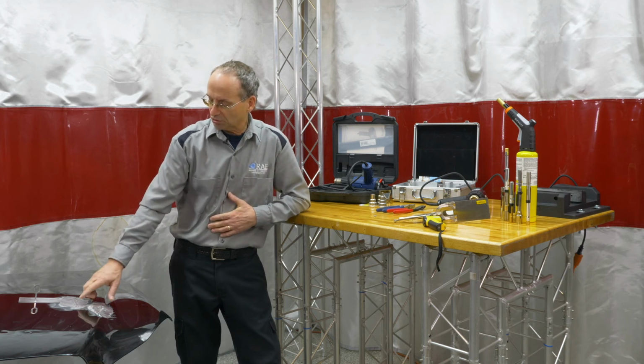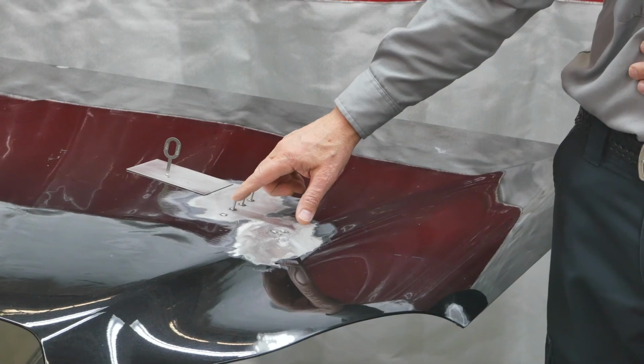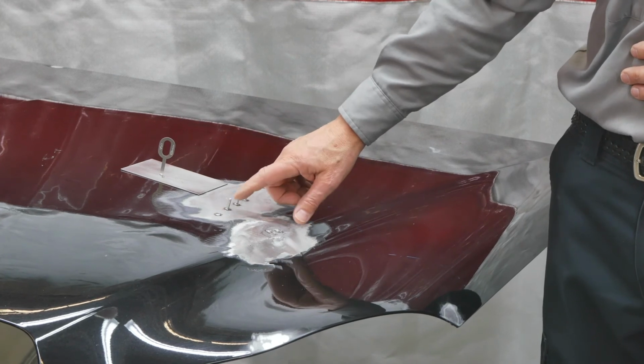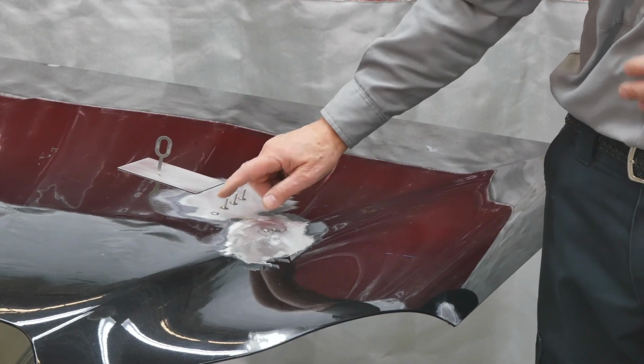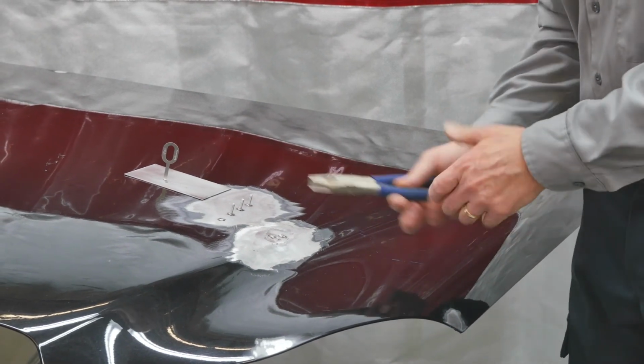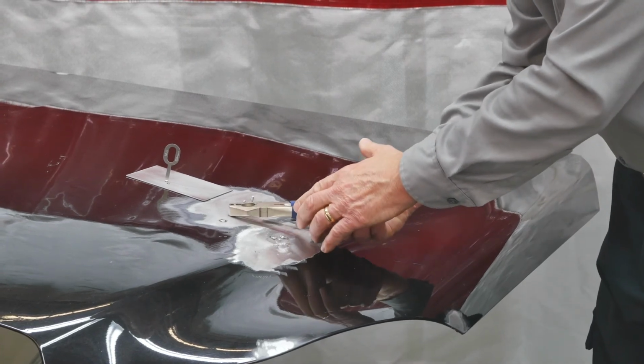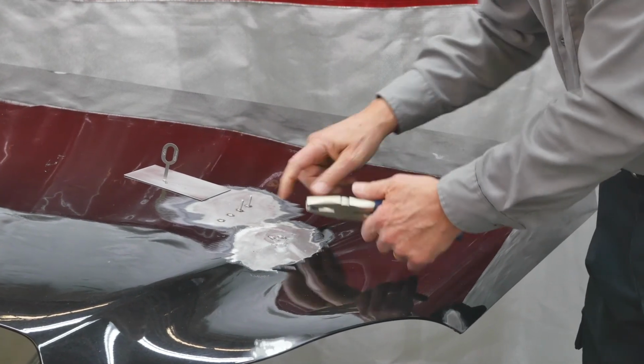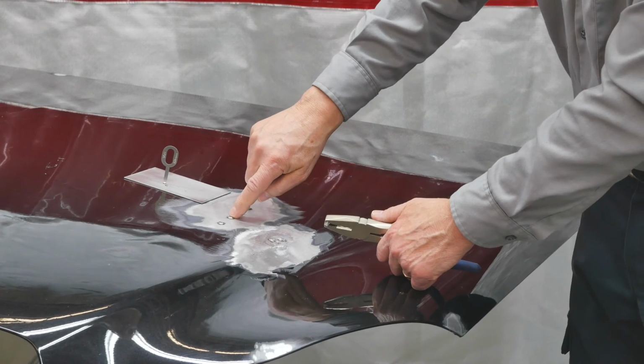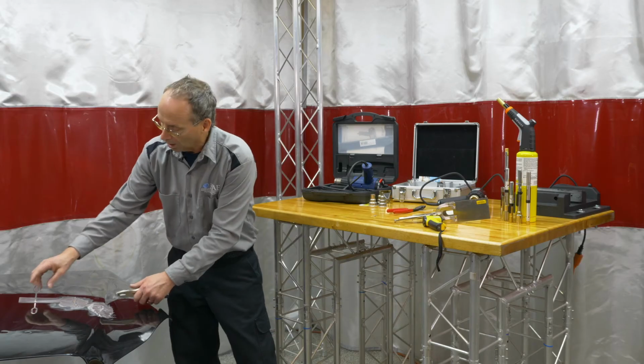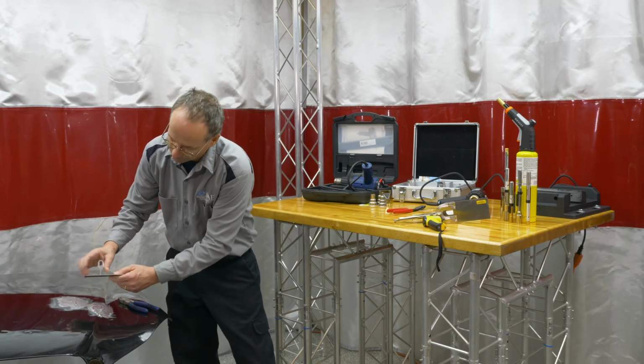So when we weld a stud on the panel to do dent repair, that is why you have to be very careful, because if we take one of these and instead of cutting them off, this thing ends up pulling off, you've actually taken out a chunk of aluminum of the panel. On this particular one, we'll get a close-up view of this.